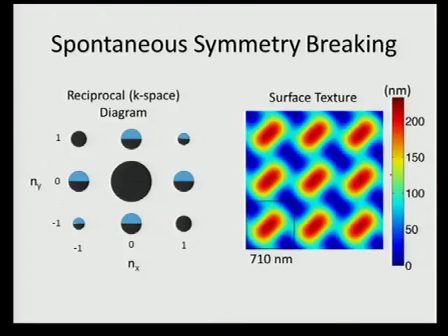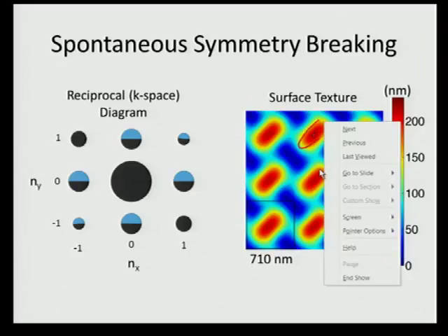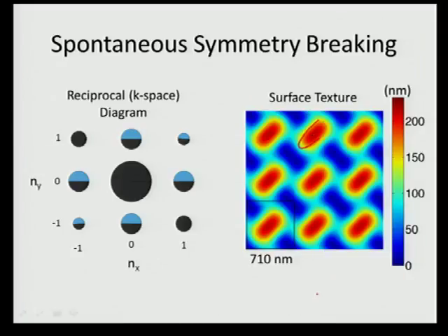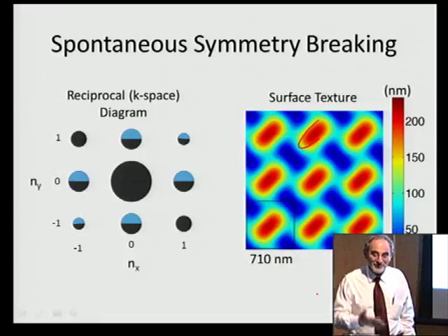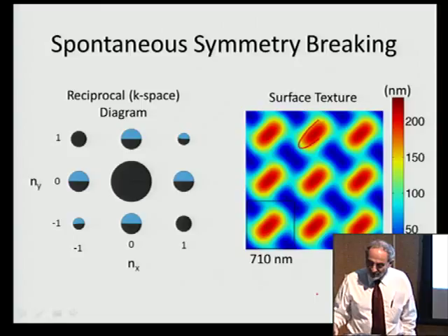We have found some unusual thing. There seems to be, in this mathematical problem, some spontaneous symmetry breaking. The thin film will absorb the most light when the surface texture is somewhat asymmetrical. In this case, it's elongated, which is very puzzling. When my student first got this, I said, this is asymmetrical. You expect me to get in front of a big audience and tell them it's asymmetrical, and we don't know why it's asymmetrical? So we don't quite know why.